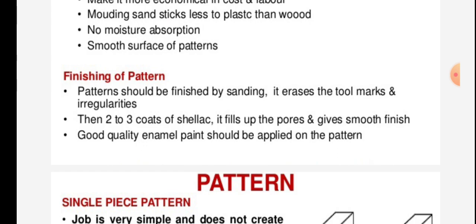For finishing of a pattern, it should be finished by sanding to erase tool marks and irregularities. Then two to three coats of shellac are applied to fill up the pores and give a smooth finish. Finally, good quality enamel paint should be applied on the pattern.